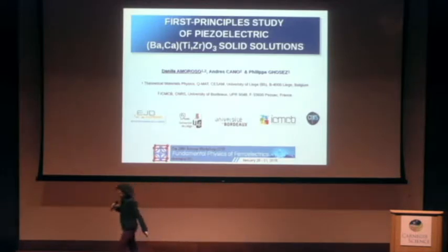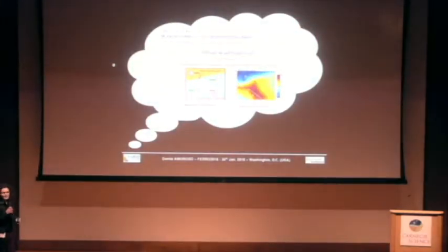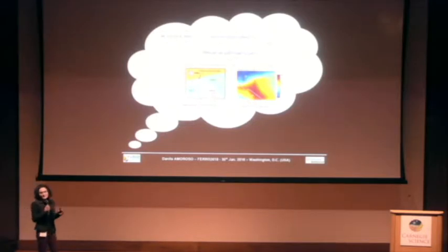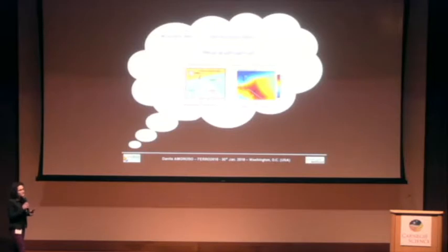So at first, the reason why we decided to get involved in this theoretical characterization of BCTZ solid solution is that we know that nowadays the community is running for the search of high-performing piezoelectrics without the use of lead. And almost 10 years ago, Liu and Ren found a candidate in this barium calcium titanium zirconate solid solution, with actually low concentration of calcium and zirconium doping of BTO.